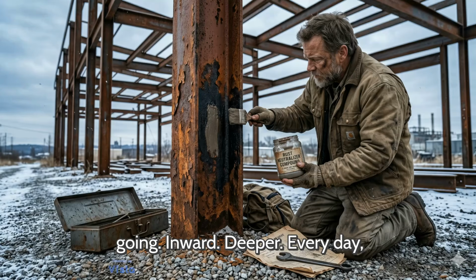It keeps going, inward, deeper, every day. The reaction front pushes further into your metal, converting more steel into more rust, expanding in volume, cracking the surface above it, letting in more moisture, accelerating the whole process. This is why painting over rust never works. You're not sealing it. You're trapping moisture underneath and feeding the reaction in the dark where you can't see it. Two years later, you peel that paint back, and there's twice as much rust as before. The contractor who sold you that paint job knew this, or should have.